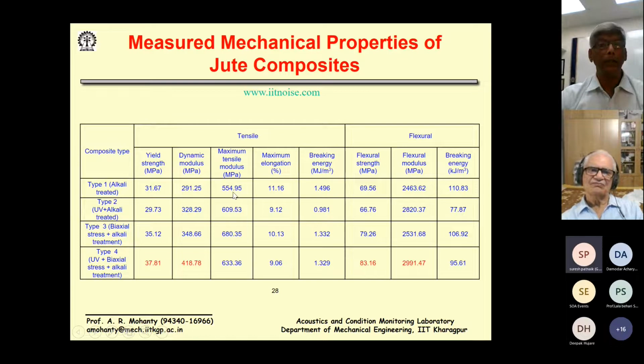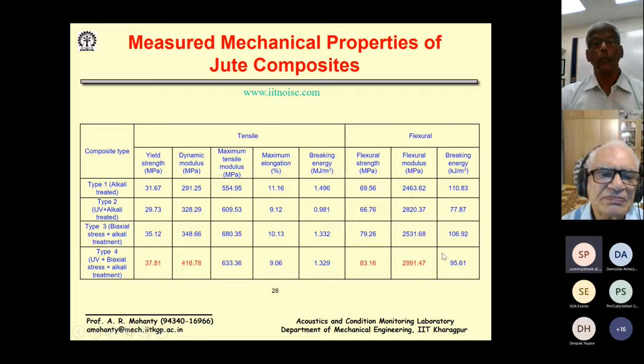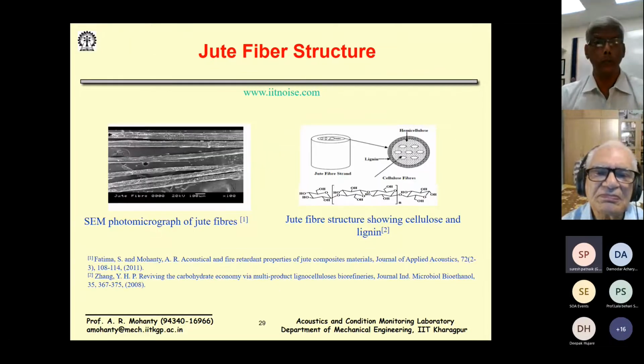If you look at the tensile strength, okay, with a certain alkali treatment and under UV light, we could get the dynamic modulus about 418.78 MPa and yield point strength so much in tensile and again in flexural. So we did all these kinds of studies to find out the best way to treat and develop jute composites which will be used for noise control applications.